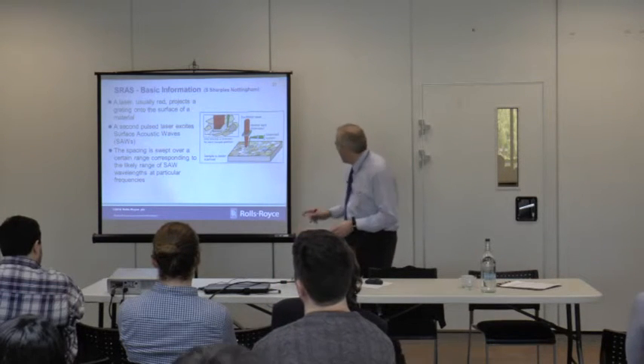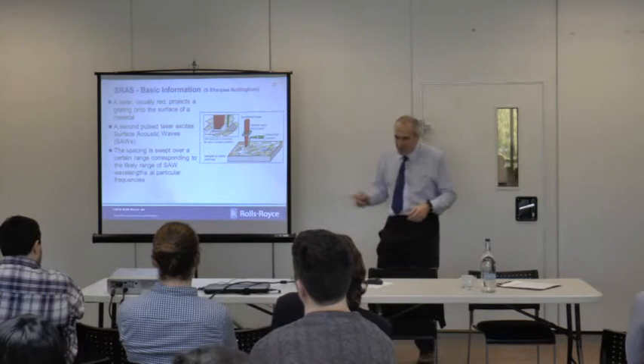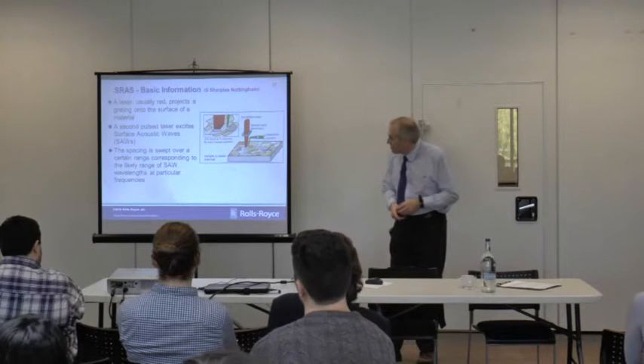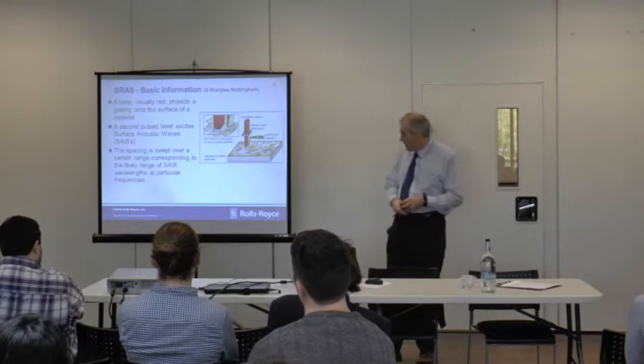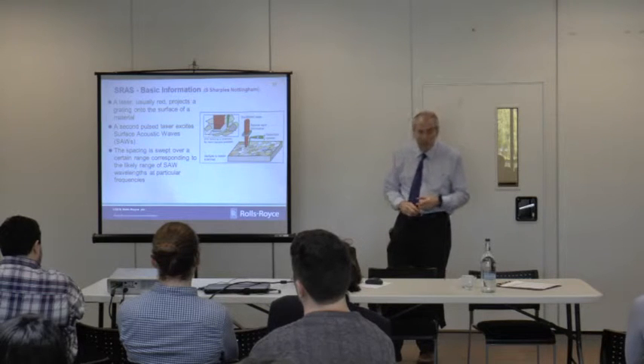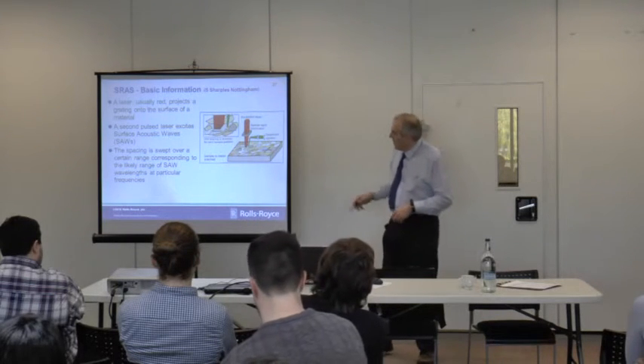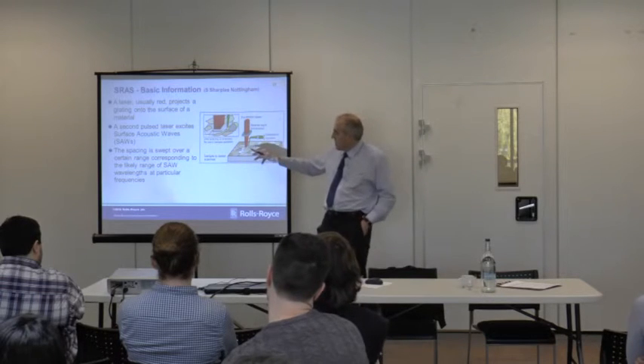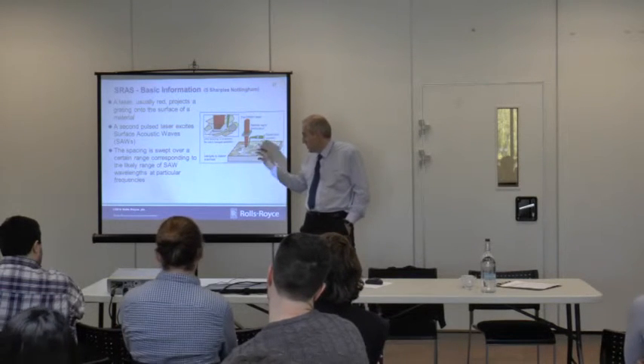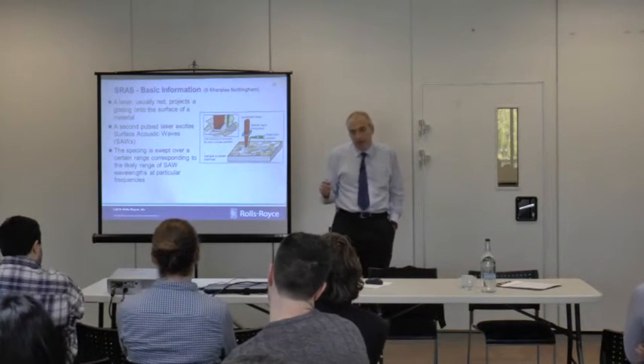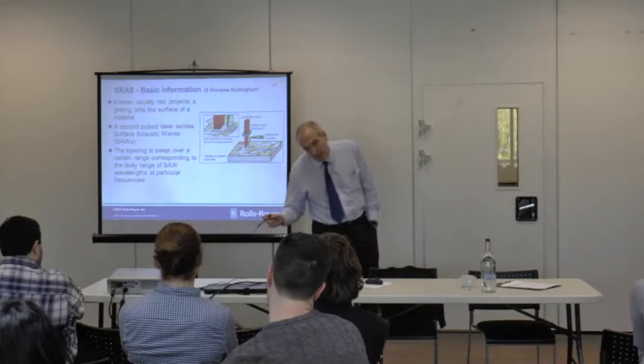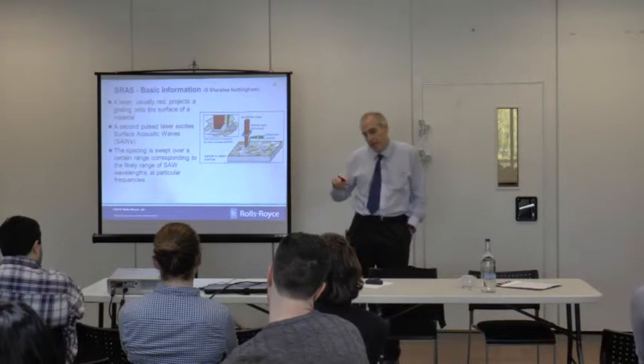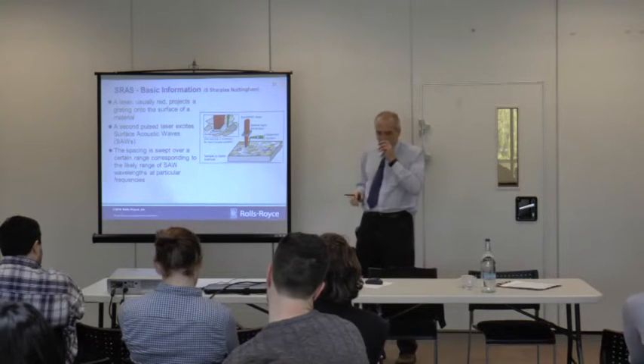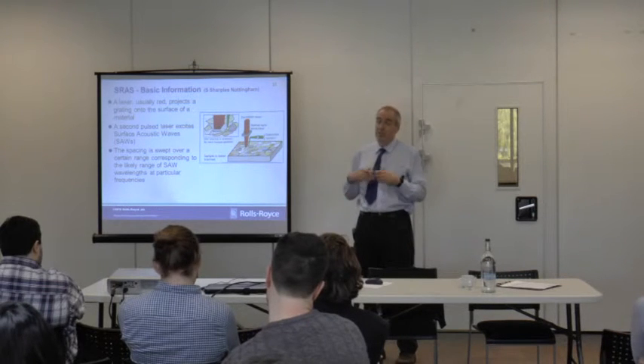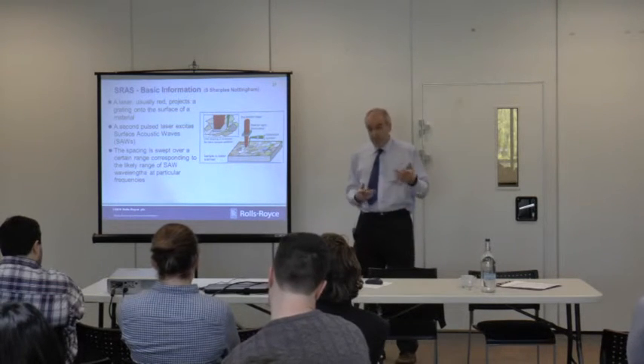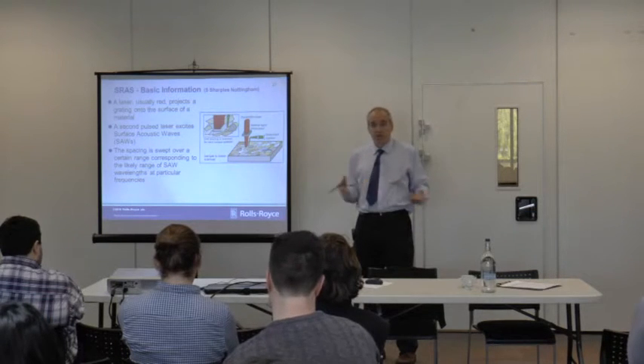very, very quick, promise. Other fun stuff we've been doing, this is with physics at Nottingham, a thing called SRAS, spatially resolved acoustic spectroscopy. We've been working with them now for quite a few years. And they use a laser to excite near-surface waves on the surface of metals. You can then use another laser to measure the input signal. It's quite clever the way they do it, but the bottom line is you can measure the wave velocity. The wave velocity is related to the modulus, and modulus related to crystallographic texture.